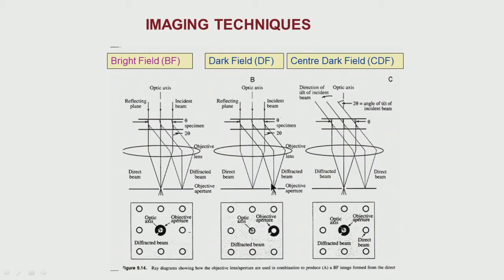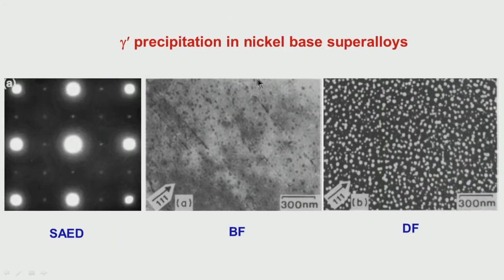Generally what happens is that if we use this sort of dark field, the beam is away from the optic axis, so the lens aberrations increase. To reduce the lens aberrations, we use a technique called centered dark field. What is done in a centered dark field essentially is that we tilt the beam so that the diffracted beam is at the center and the direct beam is away. Using this, we can get images.